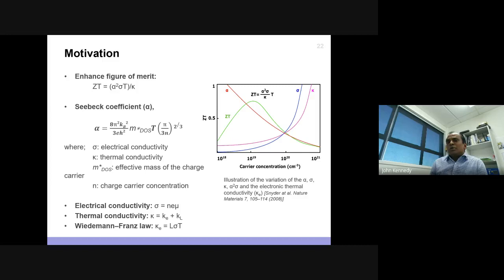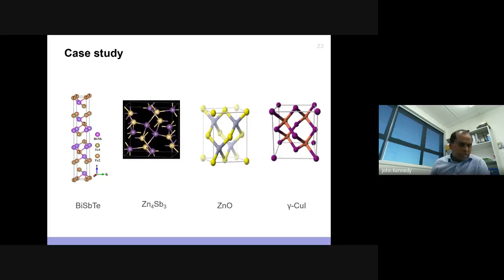What it means is you should be able to tune the electrical conductivity and the effective mass, which means you can look at the number of electrons, and also you can do some doping strategies to do that. Because the electrical conductivity is N e mu, you have the mobility and the number of electrons as well. We didn't touch the thermal conductivity because it's very much known. We looked at mostly tuning the electrical conductivity and the Seebeck coefficient. These are the two parameters we thought let's have a go at, right? Because you can actually make amorphous, polycrystalline and crystalline materials as well. So we concentrate most of our work there. I'll give you three case studies because of time. We looked at bismuth antimony telluride, zinc oxide, which is aluminum-doped zinc oxide, and new materials called copper iodide.